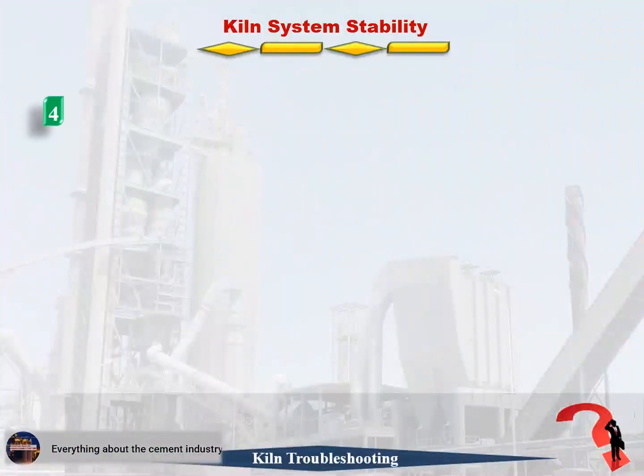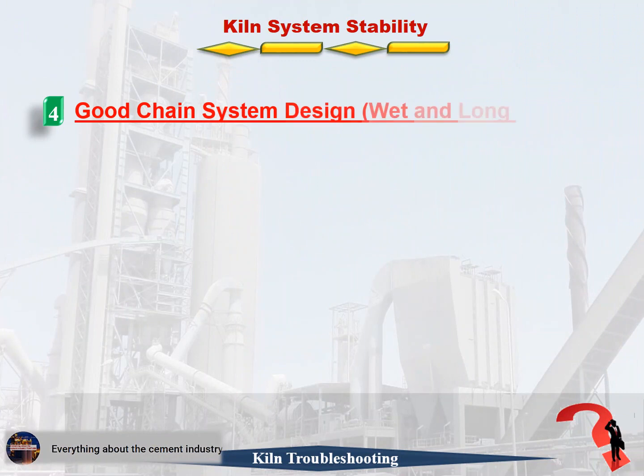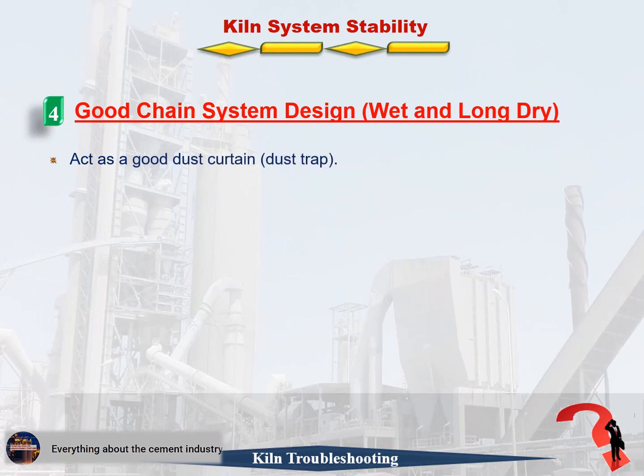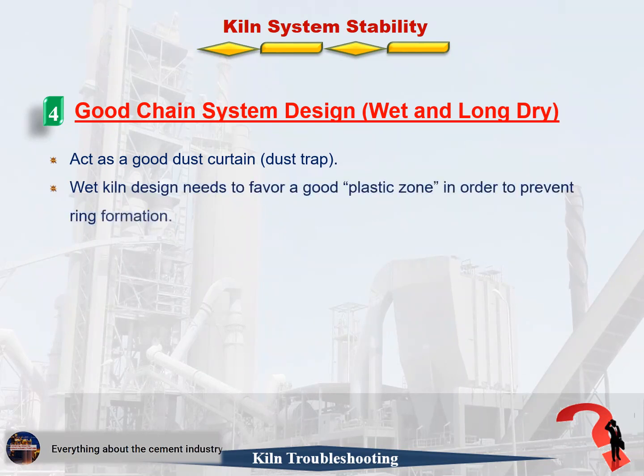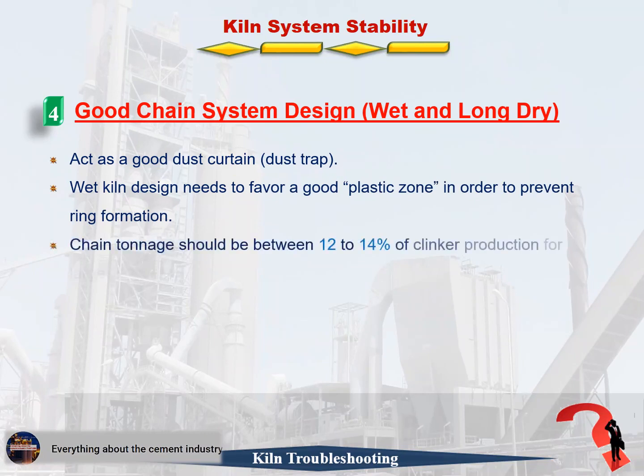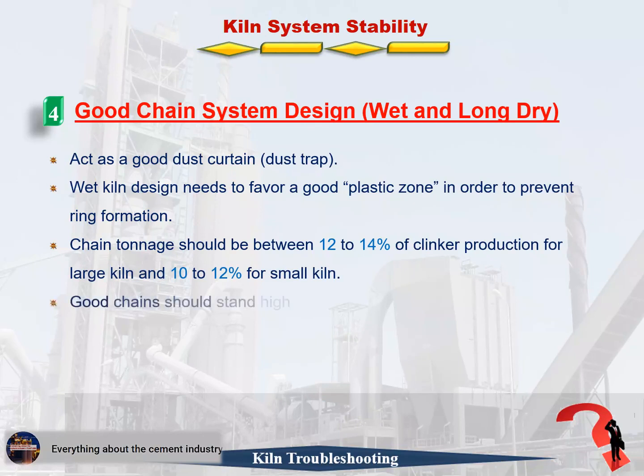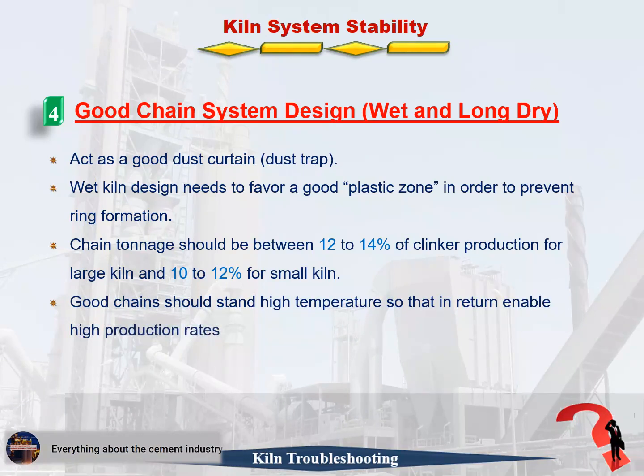4. Good chain system design, wet and long dry. Firstly, act as a good dust curtain, dust trap. Secondly, wet kiln design needs to favor a good plastic zone in order to prevent ring formation. Thirdly, chain tonnage should be between 12 to 14% of clinker production for large kilns, and 10 to 12% for small kilns. Fourthly, good chains should stand high temperature, so that in return they enable high production rates.